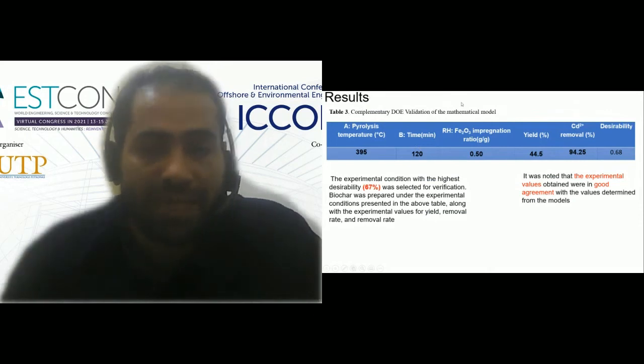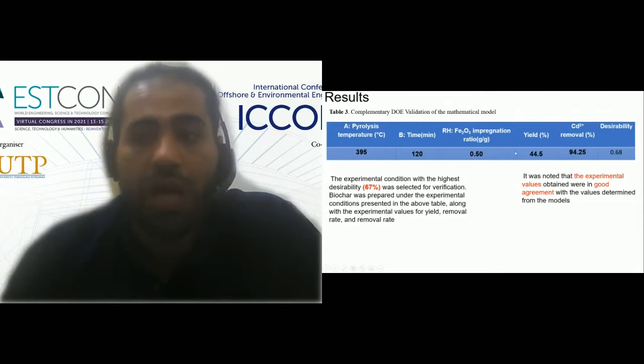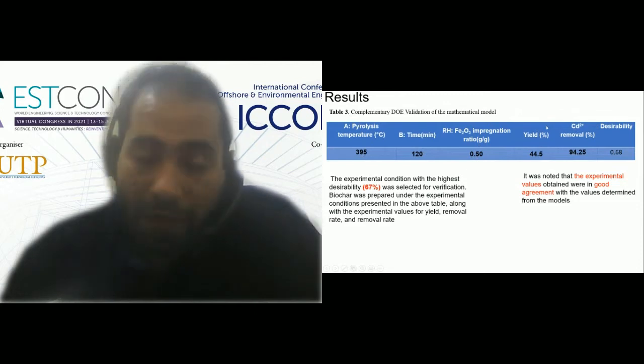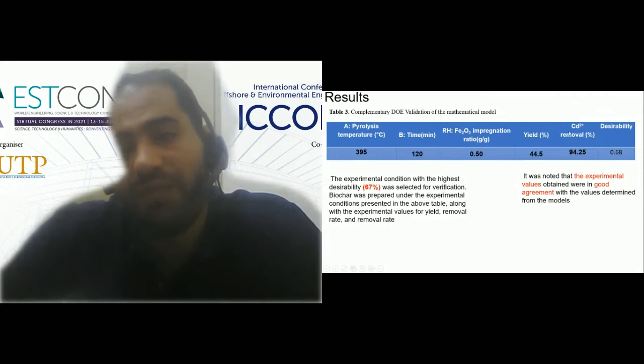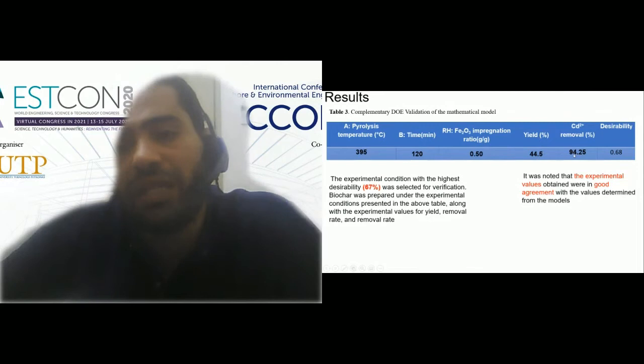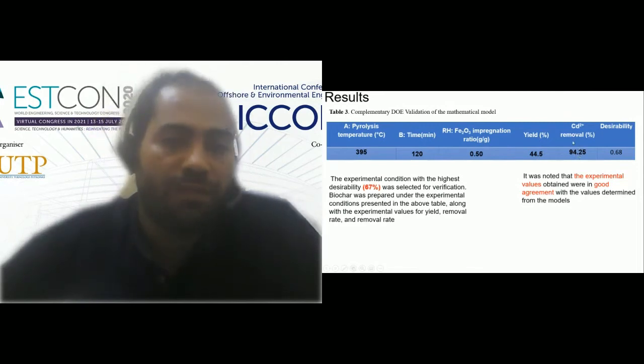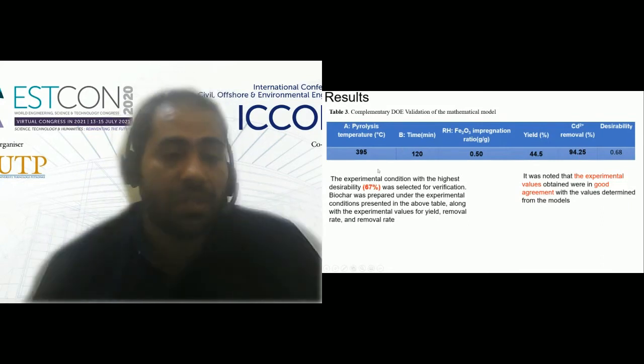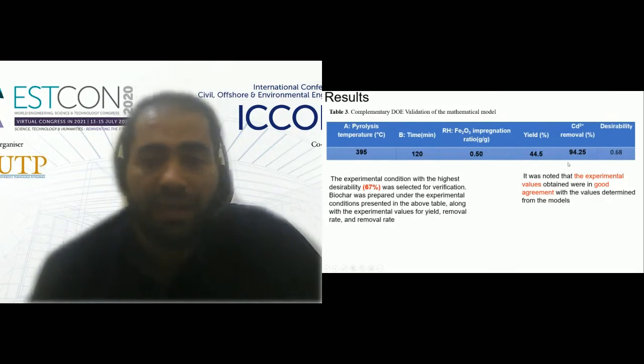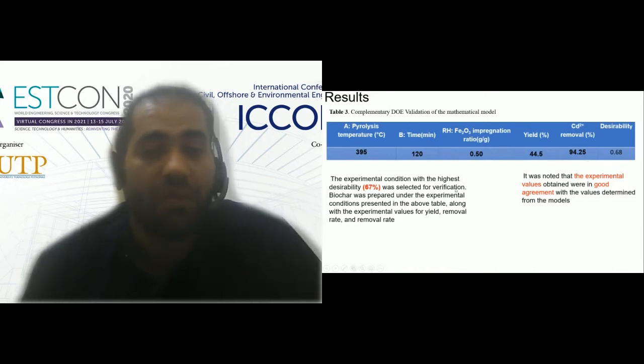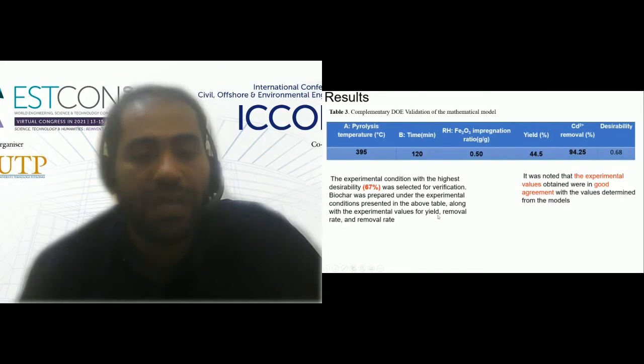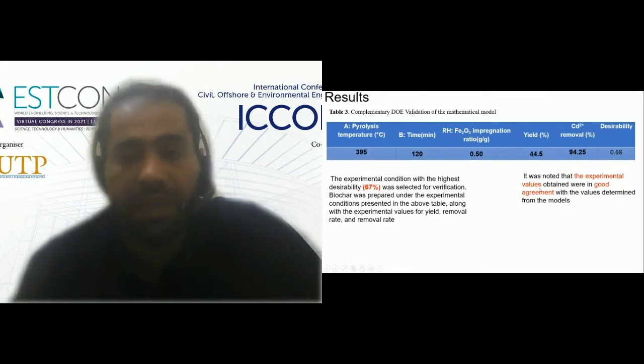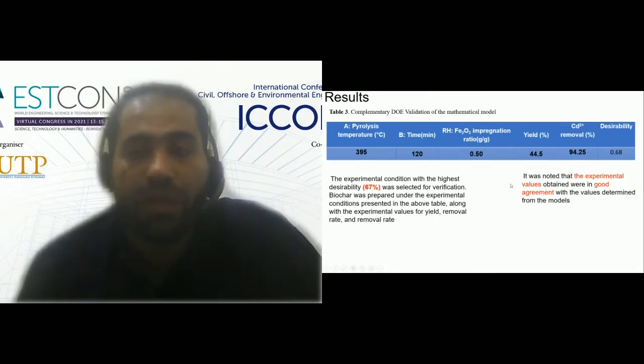Now the optimum result of validation from the mathematical model. We get the optimum temperature of 395, 120 minutes, 0.5 as the impregnation ratio, and the optimum results for the two responses: 44 for the yield and 94.25 for the cadmium removal. From this table, as you can see, the experimental condition with the highest desirability was about 67 point something. The one with desirability 67 was selected for verification. The biochar was prepared under the experimental conditions presented in the table, along with experimental values for yield and removal rate. It was noted that the experimental values obtained were in good agreement with the values determined from the models.